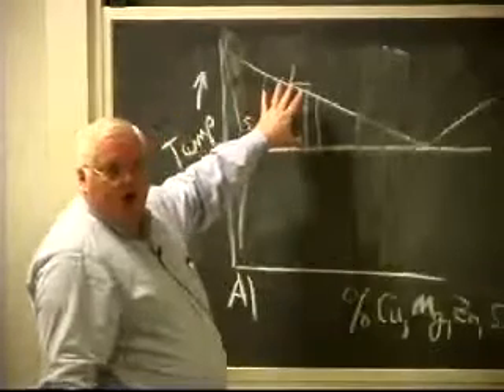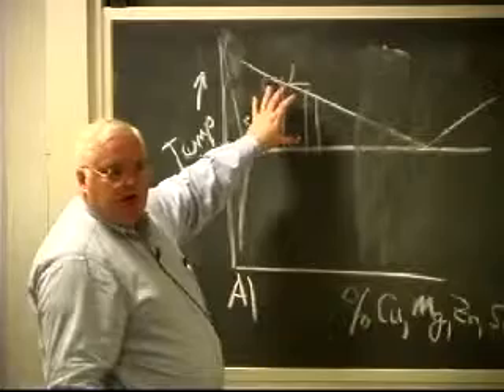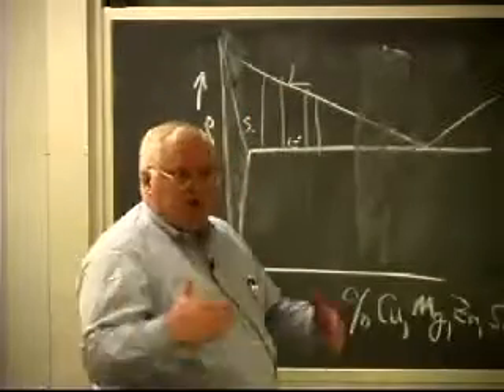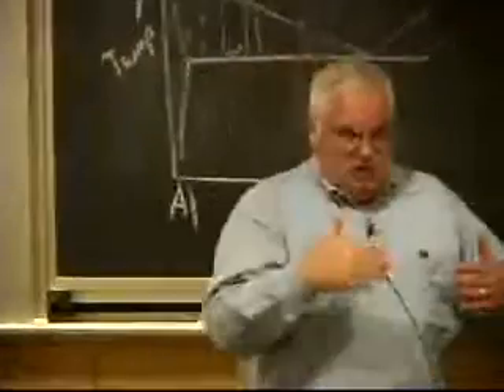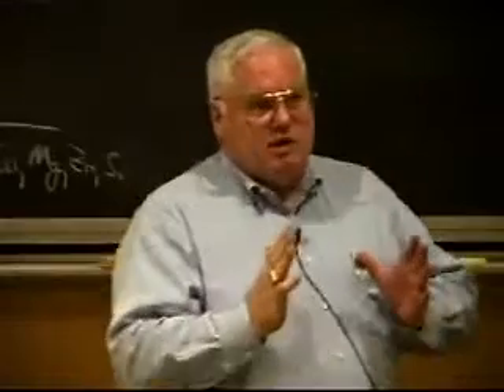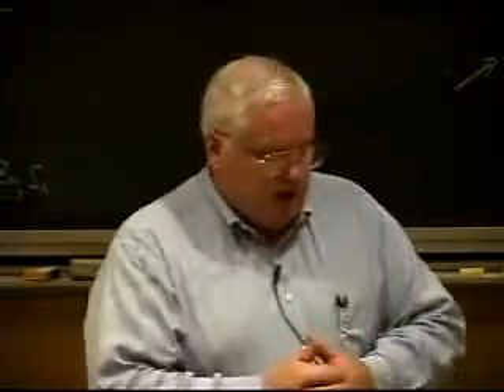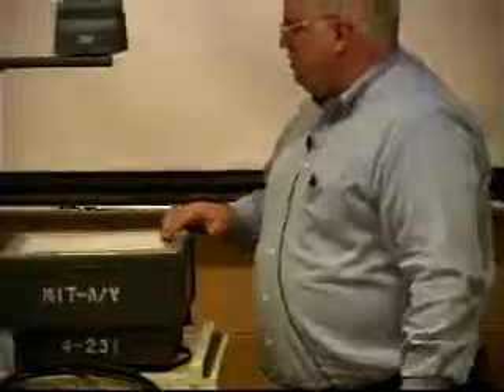If I have a very wide mushy range where I have liquid and solid coexisting, that means that on freezing of that weld, I will have a wide temperature variation where it's mushy, and I'll have a lot of thermal contraction, a lot of thermal strain, and I'll basically get cracking. What we call hot cracking, or what a caster calls hot short cracking. Okay? We call it liquation cracking in welding, but casters call it hot shortness.